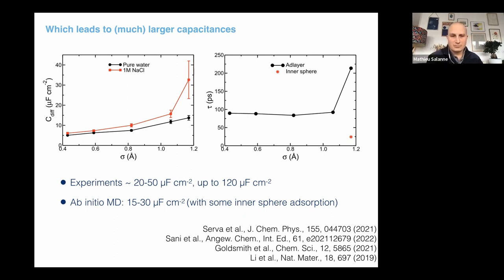There are also some ab initio molecular dynamics that were made in the past 3 years. So one by the group of Arabella Celoni, and the second one by Jun Cheng in China. In both cases, they get numbers around 15, 30 microfarads per square centimeter. But the comparison is not so easy because in ab initio MD, they just put some counter ions on the electrode. And so the concentration of ions is not controlled. So we cannot know whether the comparison is relevant or not. But at least the numbers point towards the large end of the numbers we had in our simulations.